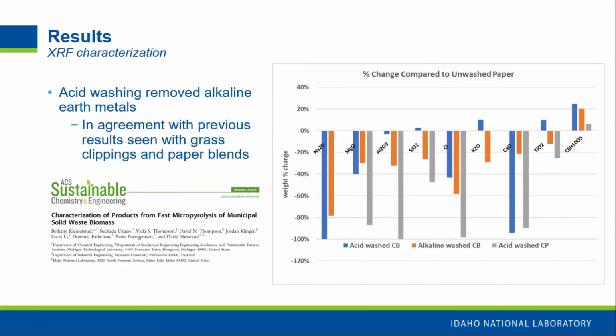One other thing we've done is a little more investigating into why we have some of these increased yields with acid washing specifically. We did find that acid washing, according to these XRF results, removed alkaline earth metals, and that's shown here with the bars going into the negative. We also enriched in cellulose, which is shown on the far right here. So basically we're getting rid of a mass of these alkaline earth metals and enriching our concentration of cellulose. This is in agreement with some previous results where we've done grass clippings and paper blends with an acid wash as well, and it's in agreement with those results that we're decreasing our amount of alkaline earth metals.